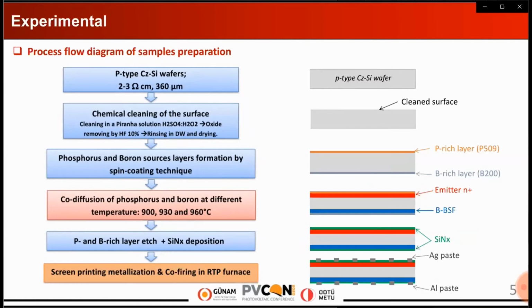Before any process, the wafers were firstly cleaned chemically in a Piranha solution, followed by oxide removal in diluted HF acid, rinsing in deionized water, and drying in nitrogen flux. After that, phosphorus and boron source layers were respectively deposited on front and rear sides of the wafers using the spin coating technique. The spin-on dopants used in our experiments were P509 for phosphorus and B200 for boron, produced by Filmtronics Inc.